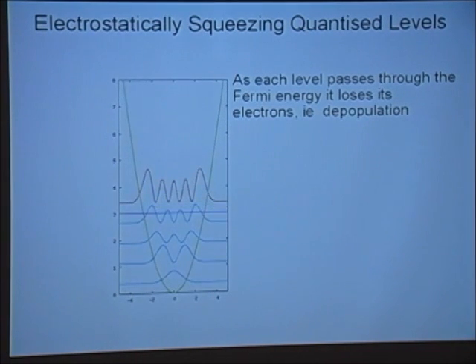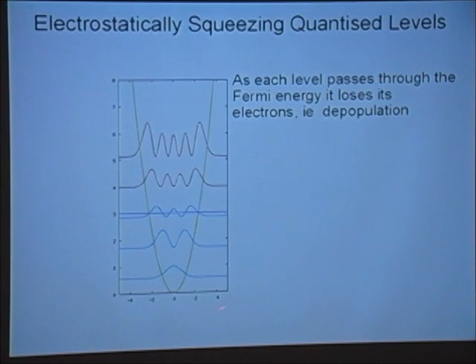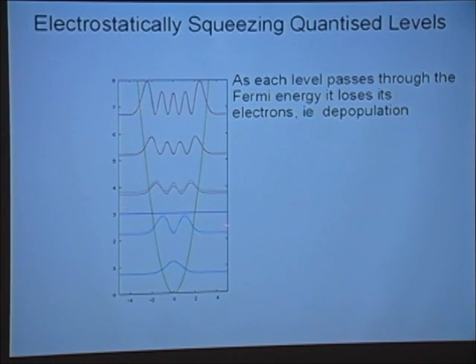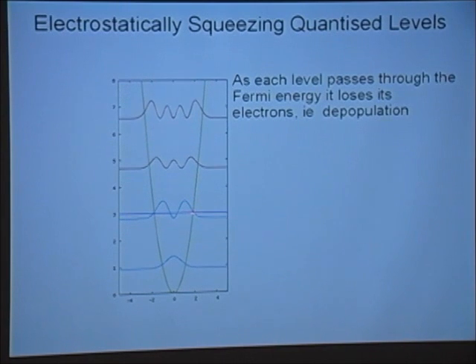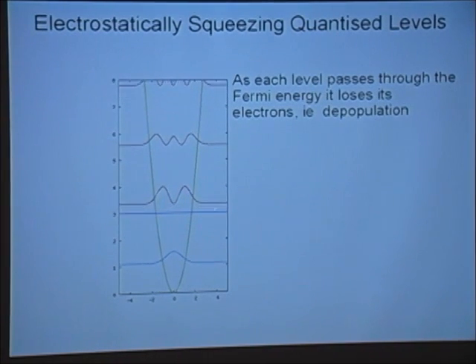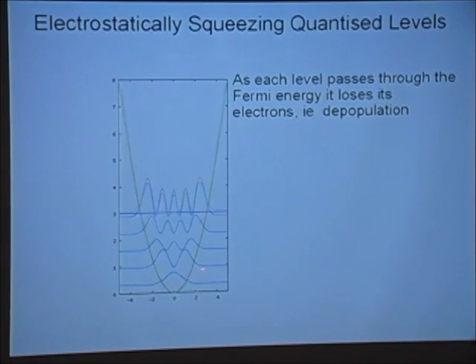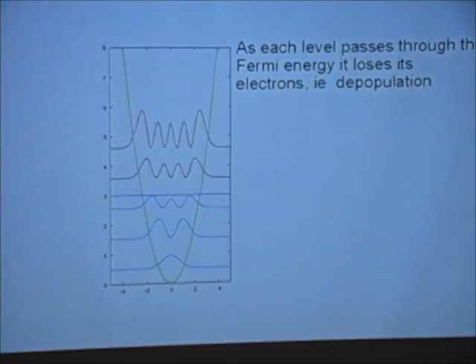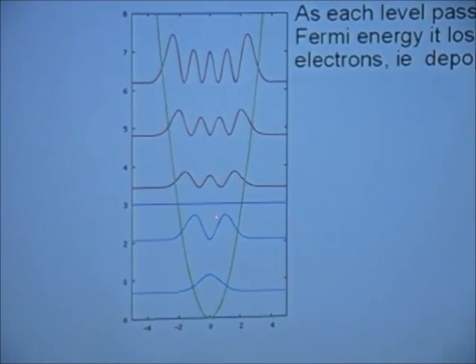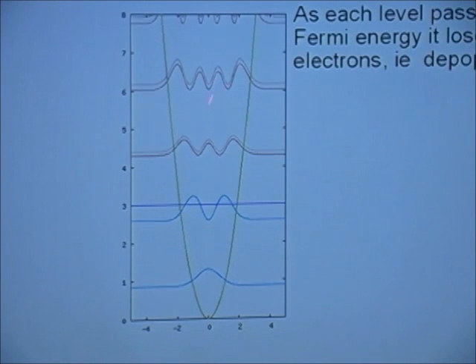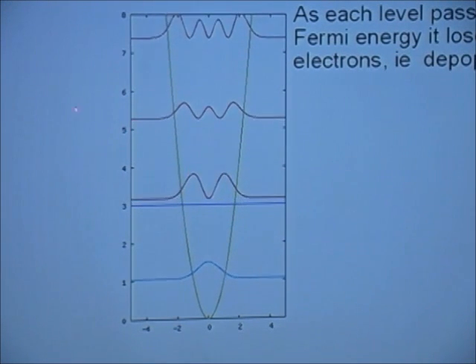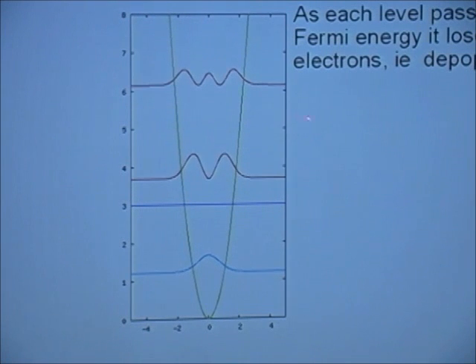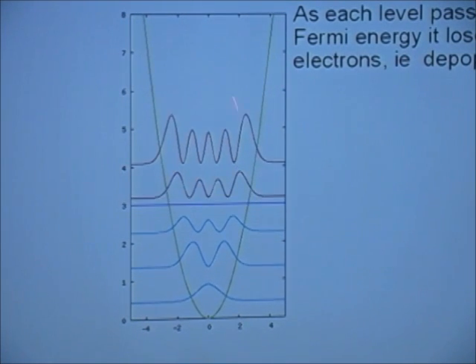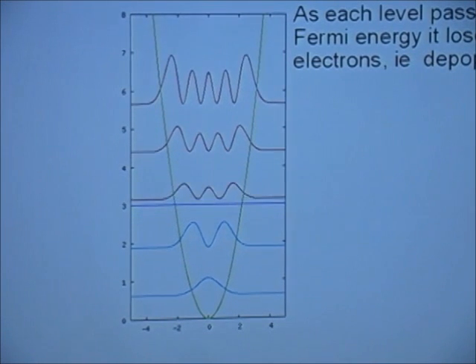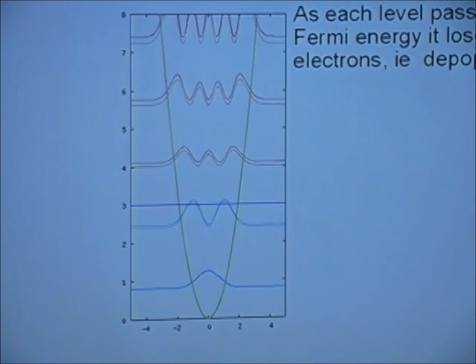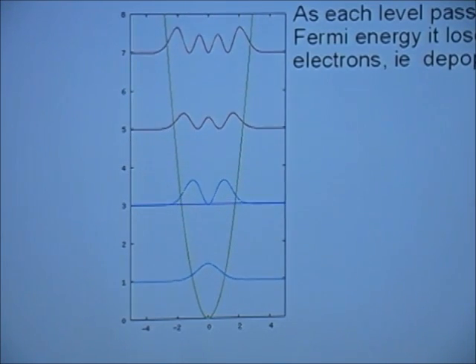And this is what happens. These are the levels. That's the Fermi energy there. Below the Fermi energy, all the levels are full. Above it, they're empty. And you can see what happens here. As we squeeze this, we narrow the electron gas, we increase the energy of the levels. As they go through the Fermi energy, they lose their electrons. We've shown this by the fact they change color. So they come back now. There we go. Up they go. And as they go through the Fermi energy, they lose their electrons. So we can study the transport processes of the electrons as this happens.